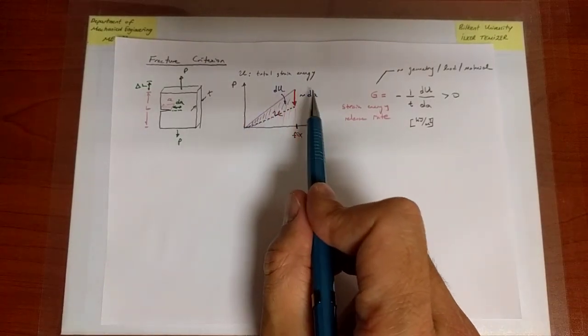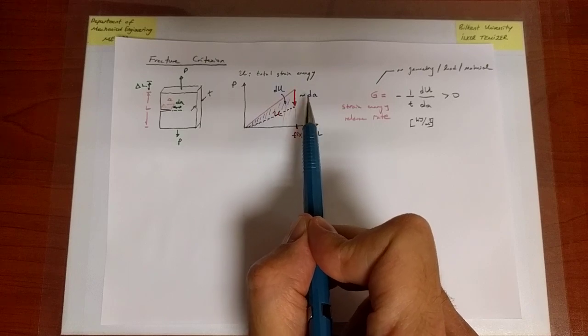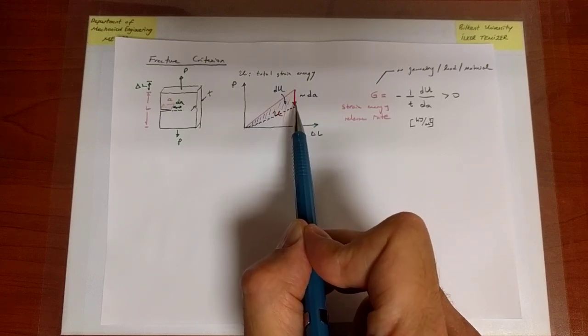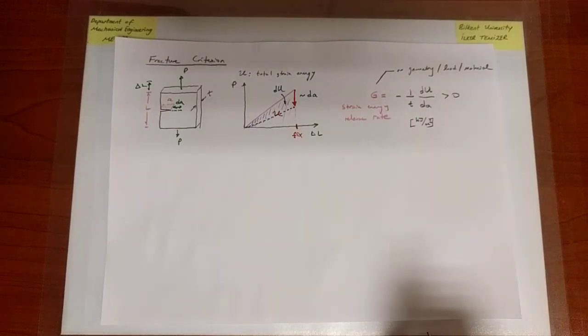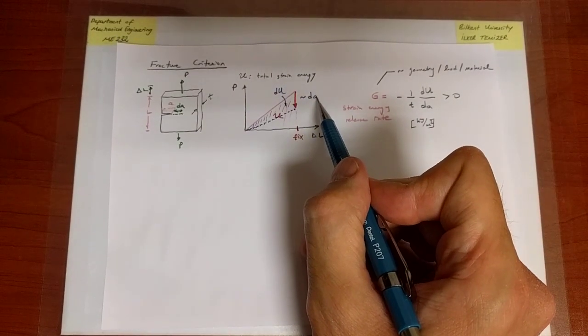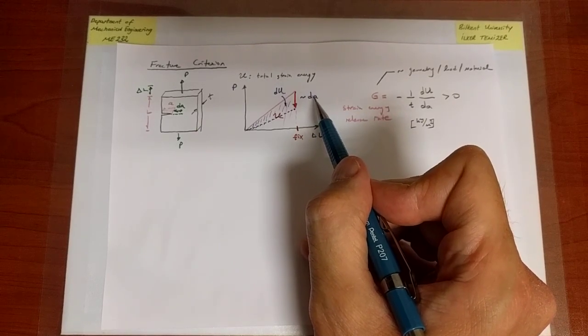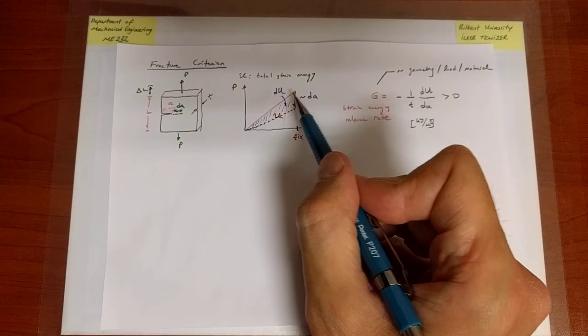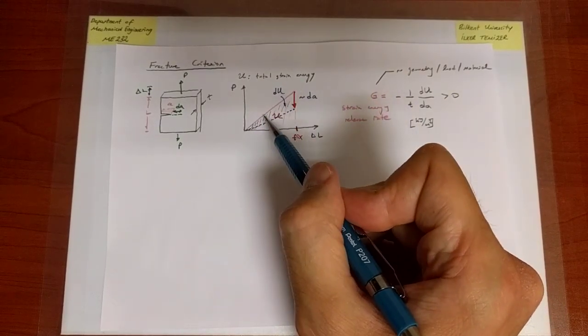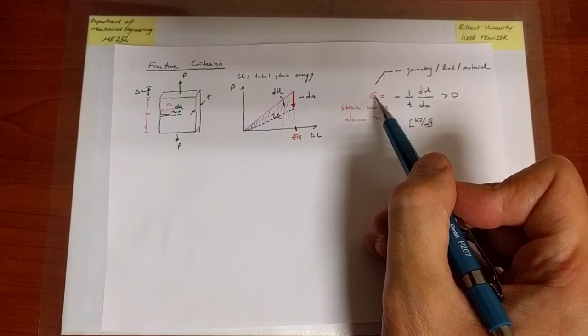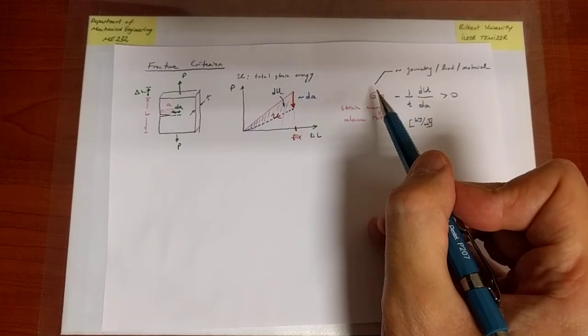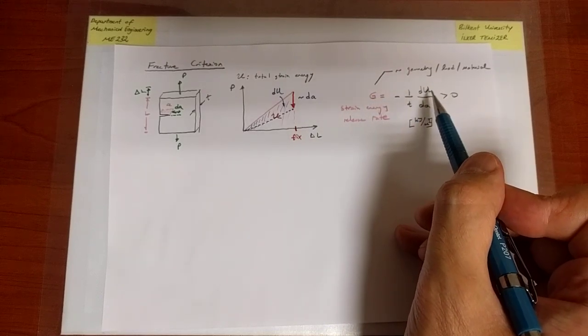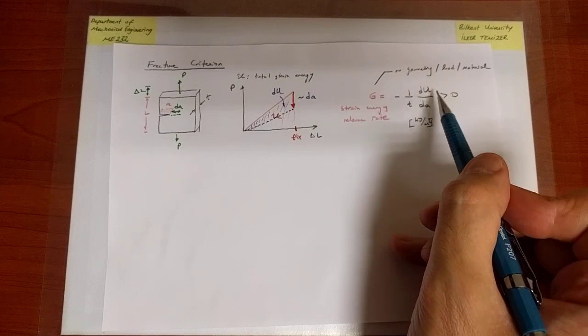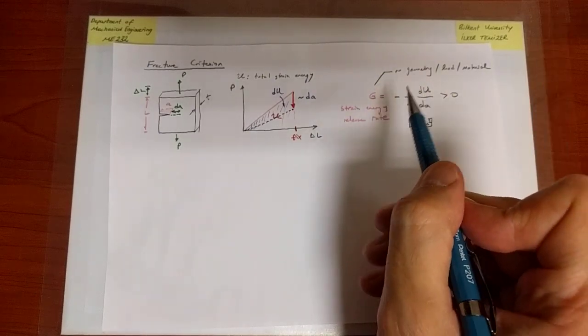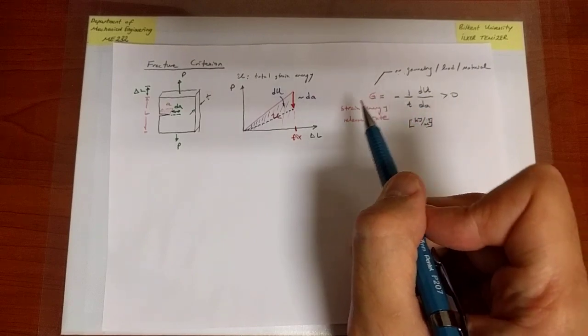What I said is I'm doing a virtual scenario. I'm assuming that the crack propagates, and the energy that is needed for the propagation of the crack, just like in the experiment with the tape and the band, is coming from the system. The crack propagates, and to propagate, remember, it generates new surfaces, and the energy that it needs comes from the system. So G is essentially the rate at which the system can supply energy into the crack propagation rate. Okay? So the rate at which the system can supply energy to the crack growth is G.